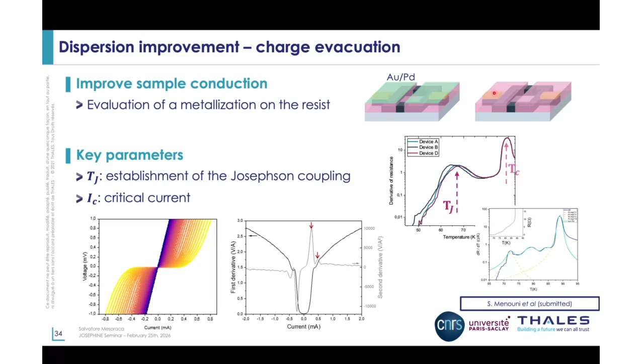So as I was saying, we made two sets of samples where we metallized the top resist in order to see if charge evacuation would improve and actually make an improvement in the dispersion of our junctions. And the other set was kept as is, so without any metallization. With the devices, we measured two key parameters, which were the TJ and the critical current. TJ is what we define as the onset of the Josephson coupling, which is effectively the second transition that we see in the RT curves. Here in the derivative, it actually shows as two peaks. So you have the first peak, which is the TC, and the second one, which is TJ.